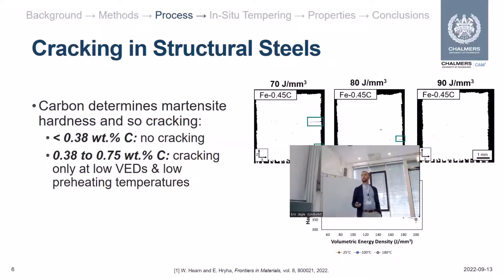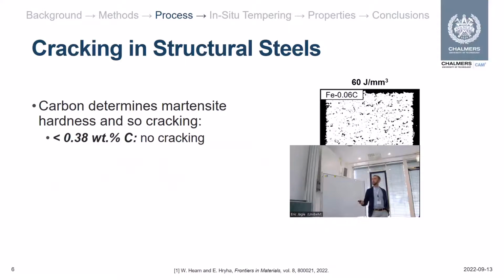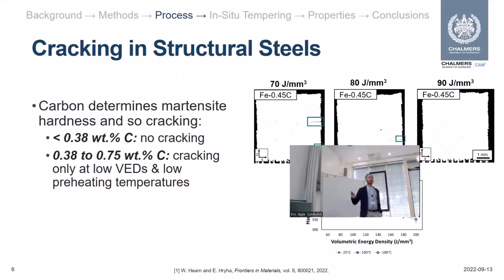Now the reason why this is happening is that by increasing either parameter, you're improving the in-situ tempering of your material. And you can see this quite easily just from hardness measurements, where as you increase your preheating temperature or as you increase your volumetric energy density, you are having an increase in in-situ tempering of your material, and that is what is allowing us to avoid this cracking problem.